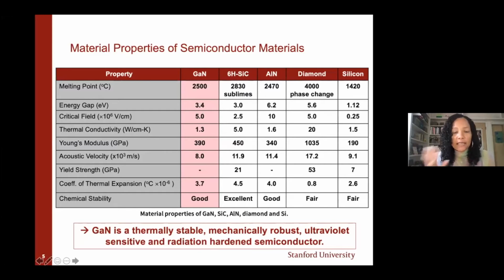And so what stands out to me, this is just a table summarizing the properties of gallium nitride in comparison to other wide bandgap semiconductor materials and also silicon. And so what stands out to me is the melting point, so 2,500 degrees Celsius. And this is due to the tight binding energy between the gallium and nitrogen atoms. It takes a lot of energy to break apart those atomic bonds.